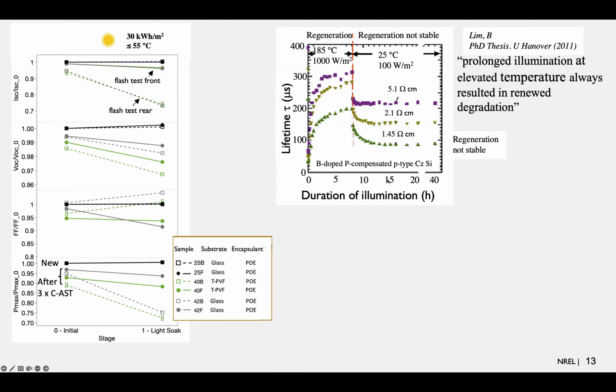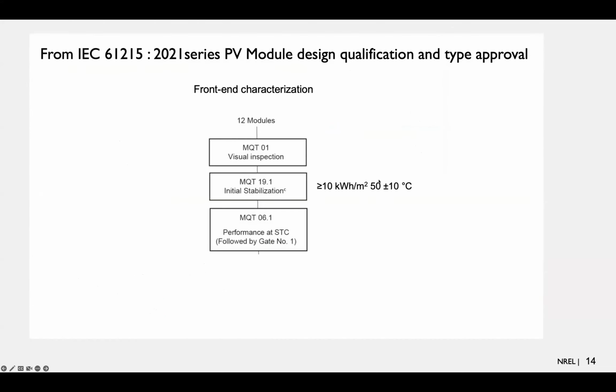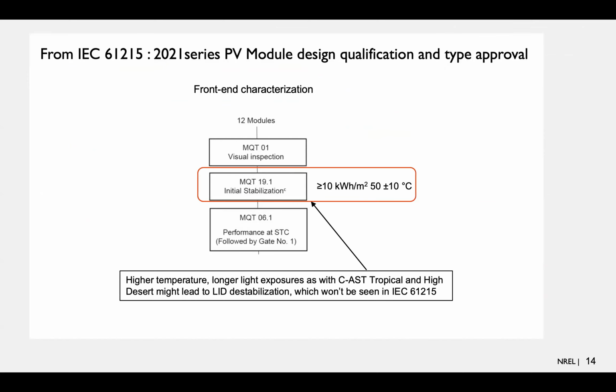So it could be that, depending on the impurities you have in the module, in the cell, you might pass a regular IEC 61215 light soak, but in real-world conditions, like building integrated PV where the module gets to high temperature, we could see some degradation even passing IEC 61215. And this graph here is to illustrate what's going on. IEC 61215 2021 series, the PV module design qualification and type approval, involves an initial stabilization where you're required to put it under 10 kilowatt hours per meter squared, 50 degrees C.